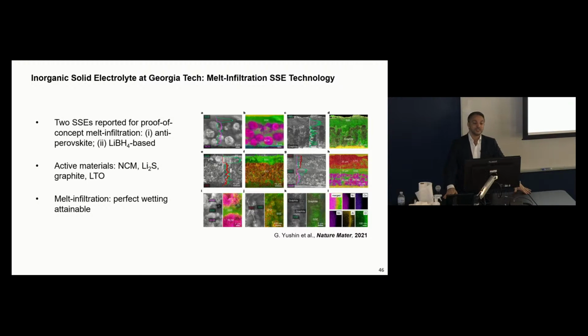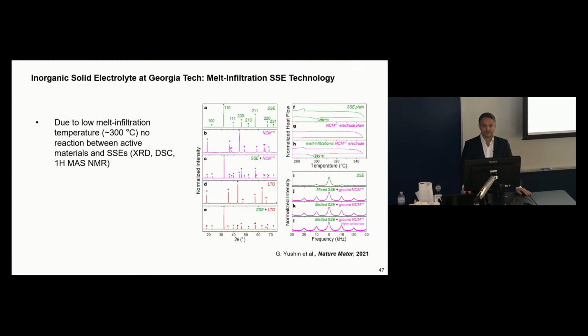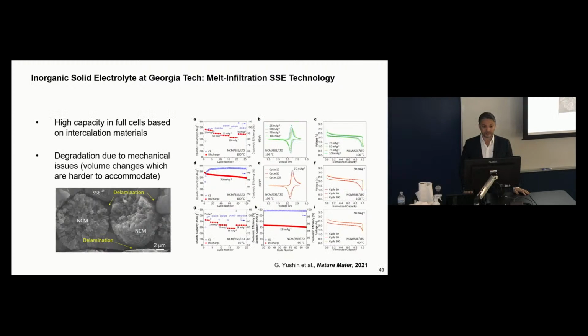So in this study, we used different types of materials. We used both intercalation materials, such as NCM, or nickel, cobalt, manganese oxide. Again, it's very common material for use in electric vehicle applications. We use graphite, we use LTO, but we also use conversion-type lithium sulfide cathode. And so because of the low melting point, right, there is no side reactions, right? If you don't have to heat the material at very high temperatures, your active material and your electrolyte won't react with each other, which is super nice. And we have multiple confirmation of that.